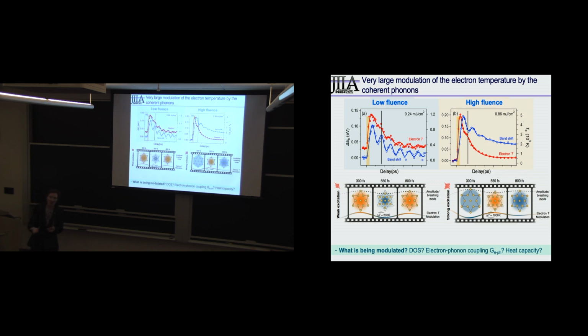when we think about heating a material with an ultrafast laser, you expect the electrons to heat up and then to monotonically cool. This shows that the electrons heat up, but then their temperature oscillates and is in phase with the breathing mode of the CDW wave. And if we do it at high fluence in this metastable state, there's a phase shift. And these temperature oscillations are quite large. They're by 200 Kelvin and up to 1,000 Kelvin in these different phases. So there really is a very, very strong coherent coupling between the electron bath and different phonon baths.